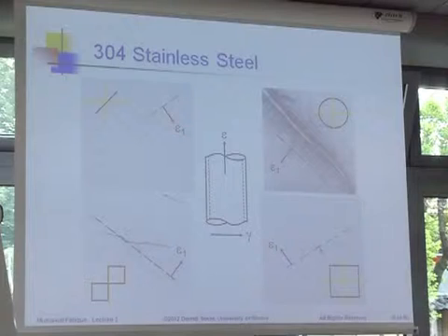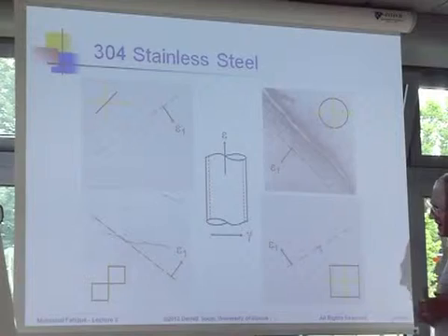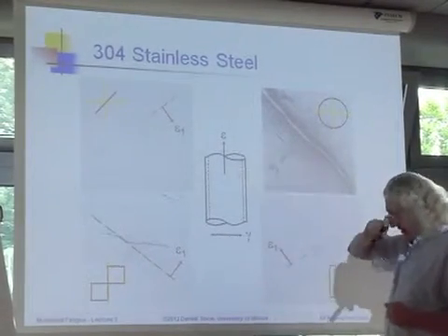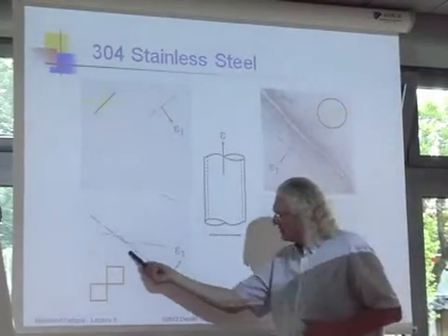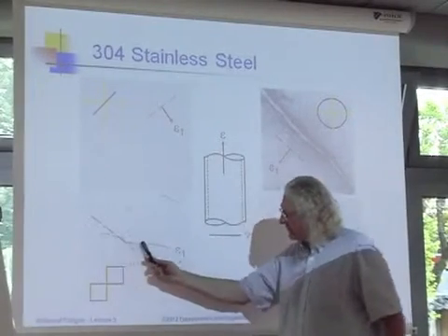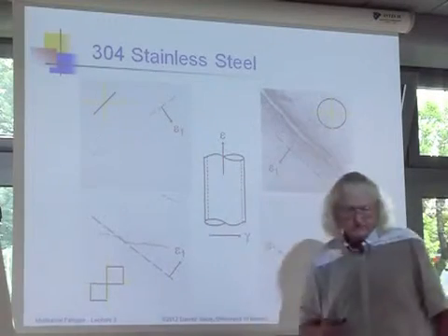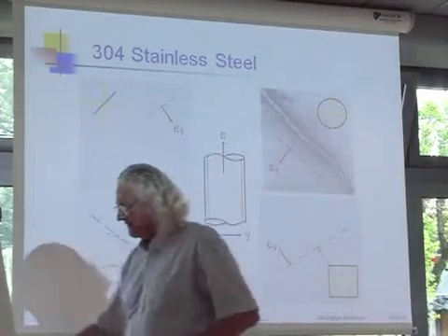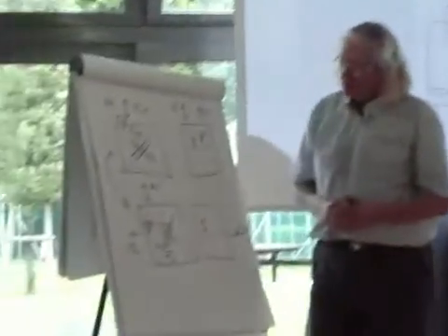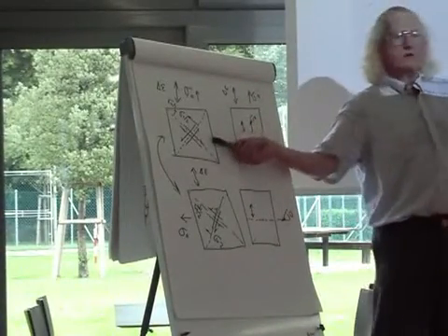So if we think about the growth on principal stress directions, that's where cracks initially form. Once a crack forms, it always tends to grow perpendicular to the applied tension load in these kind of tubular specimens, and that's what you see here. Crack initially forms here, and then after it starts to grow a bit, it turns and tries to grow in the principal stress direction or strain direction like that. So we go back to my previous chart. We make all these arguments about shear. They have to be completely wrong in this material.